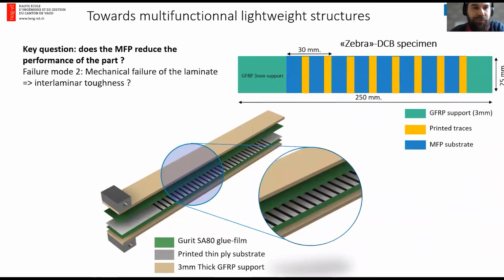Then the other failure mode could be delamination, because we introduce a pre-cured layer inside the pre-preg laminate. So we did some DCB testing using a zebra pattern, where we have this multifunctional ply, and every 30 millimeters we print a trace, and we have different trace widths that we considered. Then we measured the interlaminar toughness using DCB for all these specimens.